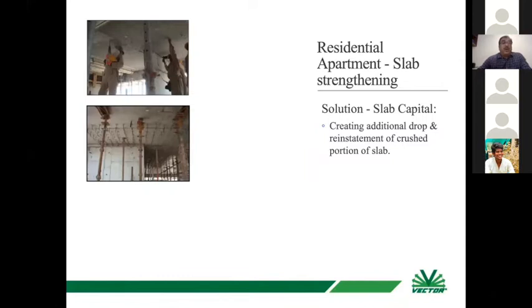The additional drop was constructed around the column by making shear connectors as per the design. The shear connectors were designed, and roughening of concrete was done for 20 millimeter amplitude, so that shear transfer was taken as 50% by the roughness, and the remaining 50% was taken care of by the shear connectors. 8.9 shear connectors were required, so we used 9 shear connectors per square meter.